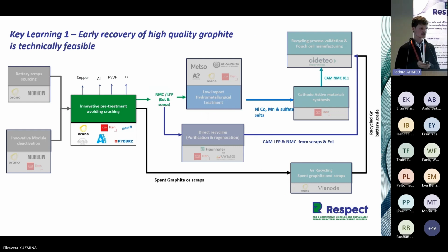The first learning message is about the recovery of high quality graphite during the pretreatment. Latest results have shown that it is possible to recover a really high quality graphite fraction quite early in the process. And this is quite good news for Europe because we have seen during the presentation of Maria that only 3% of graphite comes from a recycled source in Europe. For battery application, it's probably even lower.